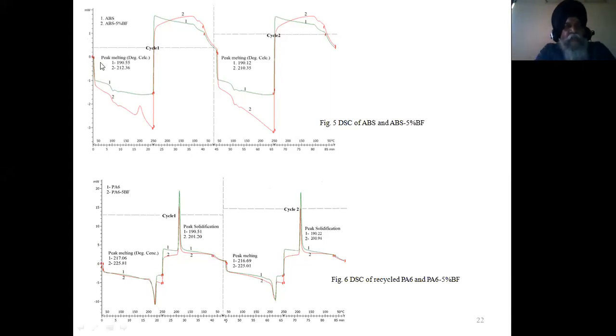Now you can well imagine on this curve, on this y-axis, we have the energy absorbing capacity. You see, with a single material, ABS, which was the primary recycled, the maximum peak temperature it was able to take was 190, right, in the first cycle, and in the second cycle again it was in the range of 190. So what observation am I getting? In these two consecutive cycles, the material is considered to be thermally stable, right? Whereas once I add 5% banana fiber into it, the heat capacity property increased, right? I can get it in the form of joule per gram also, right?